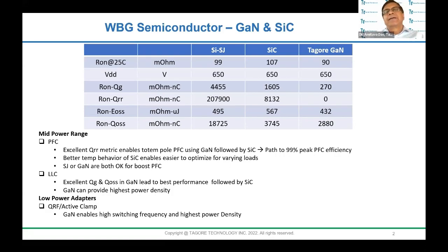Now between GaN and silicon carbide in totem pole PFC, GaN comes up with slightly better performance in terms of efficiency, but silicon carbide has much less temperature variation of RDS(on), so that's a little bit easier to optimize for varying loads. But again, I want to stress that for totem pole PFC, you need wide bandgap material. Now, compared to the traditional boost PFC, which is more driven by the EOSS metric, you can see that superjunction or GaN are both okay, where GaN might give you a little bit better performance, but superjunction will be much cheaper. So I would say that's either a wash or superjunction is probably the right choice for boost PFC.